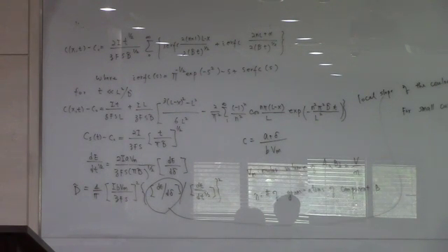Okay. And if you measure the potential with respect to square root of t, then you can extrapolate this, and this much is going to be the IR drop.